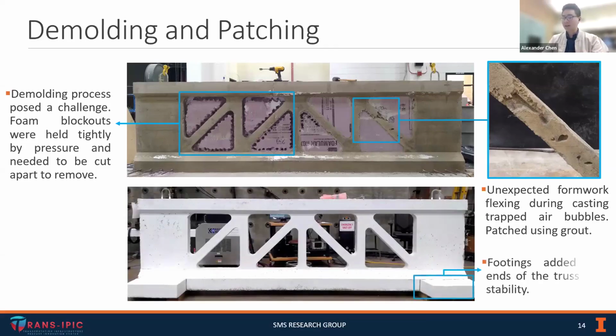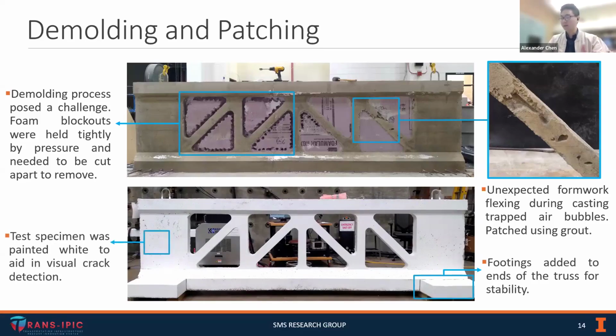You also notice that there are some bars protruding out of the specimen. We use these to later add on footings, and this is to help with the stability of the specimen. You'll see in this image of the finished specimen that we painted everything white to aid in the visual identification of cracks later during the testing process.